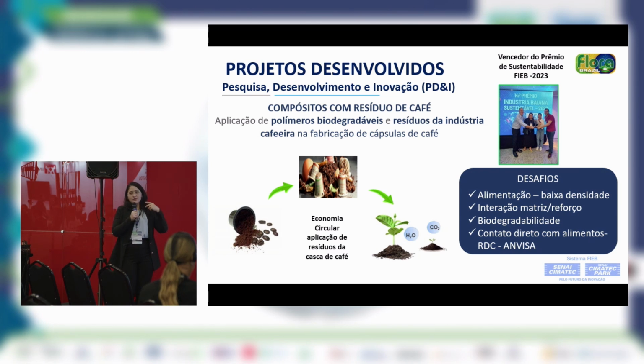feeding, since this fiber has low density. Due to the processing, the polymer of higher density tends to go down the container. The fiber stays on the surface, so we need very efficient control of the content of fiber along the composite. We must have very specific care with this feeding.